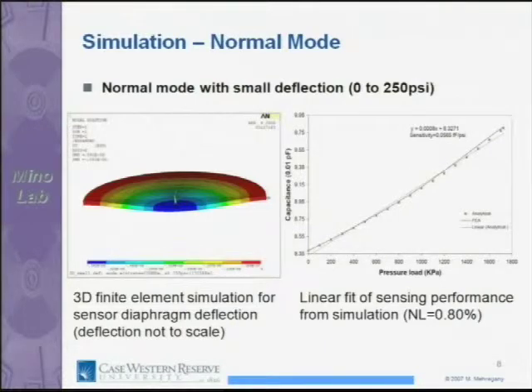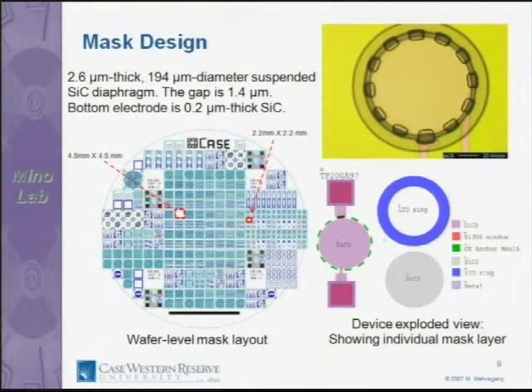What you see here, actually, let me go to this first. What you see here on top right is the picture of a capacitive surface micromachine silicon carbide pressure sensor. I'm pointing to the diaphragm. This is the pressure sensing diaphragm that sits above the silicon carbide substrate or wafer by a couple of microns. When pressure is applied, this diaphragm deflects, and the gap under the diaphragm to the substrate is modulated. So we essentially treat the diaphragm and electrode underneath sitting on the substrate as a parallel plate capacitor.